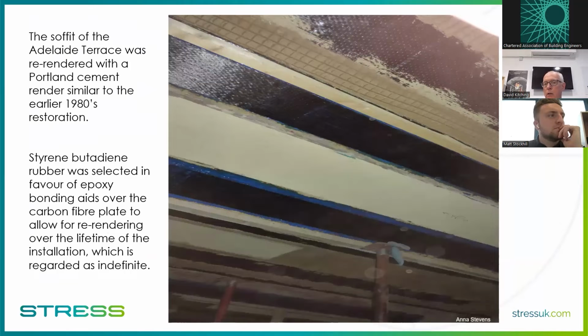Next phase, once it's all cured, is to put the render back. Now, we always sample any render, any mortar, so that we can match it. And it goes off for analysis and comes back with a mix. Believe it or not, when this came back, we couldn't believe it, but in fact it was sand and cement. So we don't know when it was done. There was no record of when it was done with sand and cement. We imagined it would be lime. So we've got to go back with the same mix, but we were allowed to put some SBR in it. The SBR just makes it slightly more workable, stickier, and will bond better to the substrate.